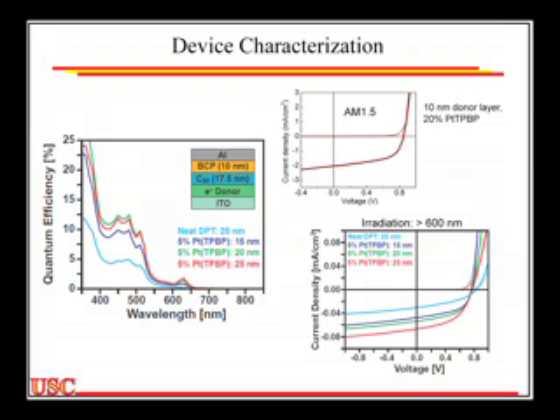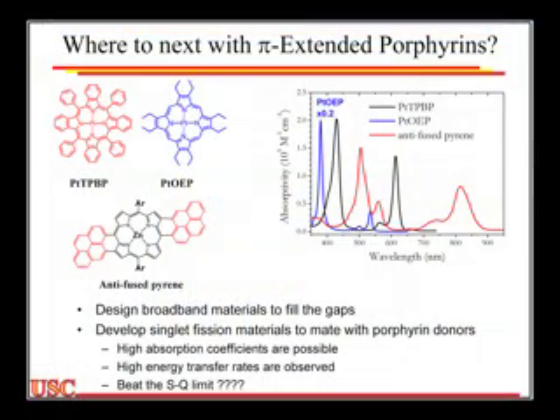The important thing is when we pump just the porphyrin, we see a nice linear increase as we increase the thickness of the porphyrin layer. So it means that as we make the layer thicker and thicker, we're getting much better diffusion than we got before. In this thickness range with just the platinum porphyrin, it would have stopped at 15 nanometers. Any increase in thickness would not have benefited me at all. So what this experiment demonstrates is we're getting the energy transfer to DPT, but the big problem is that if you remember the rates that I showed you, we have a bit of a problem, and that is that the porphyrin is in contact with this, and so this 1 picosecond as to those dimer states, we're not doing any singlet fission in that device.